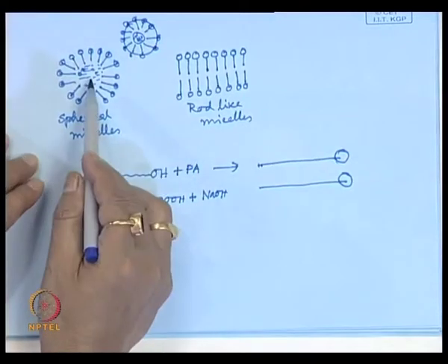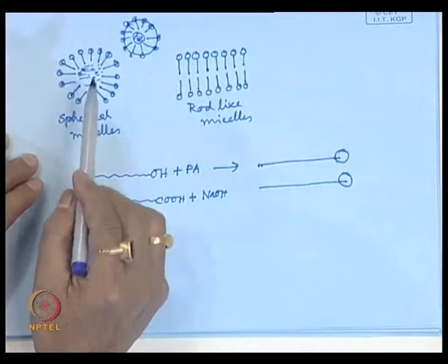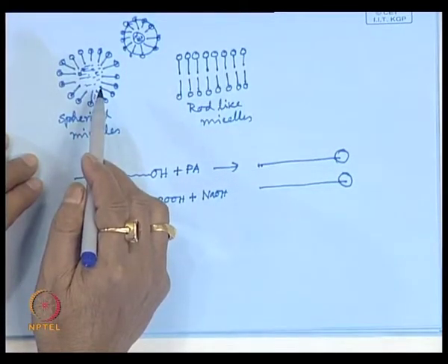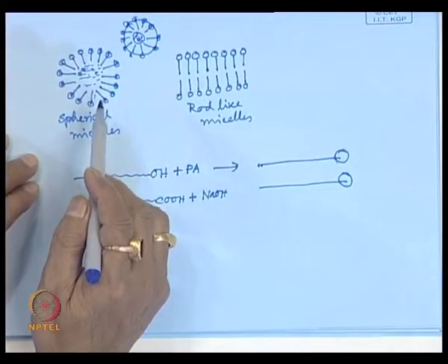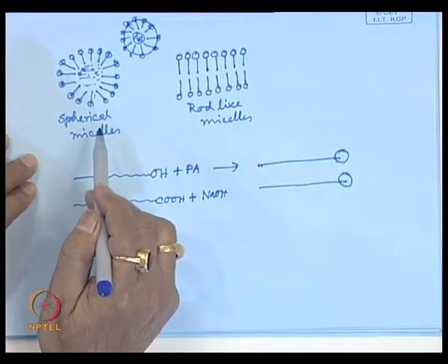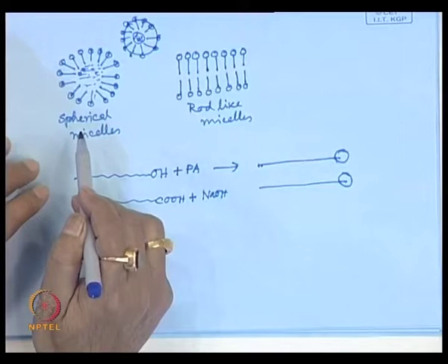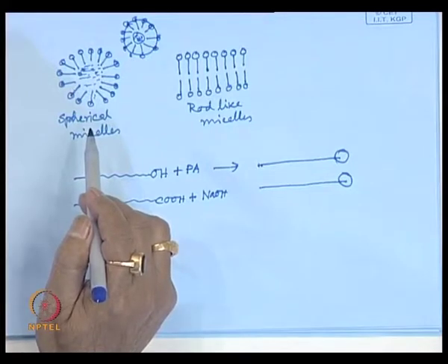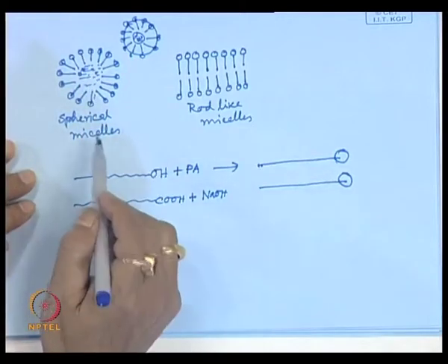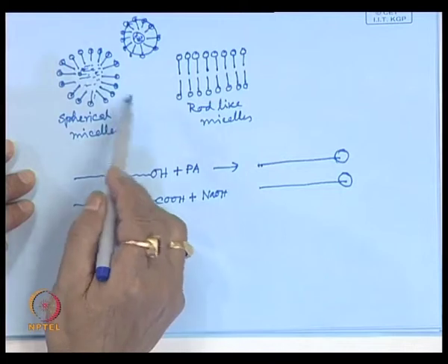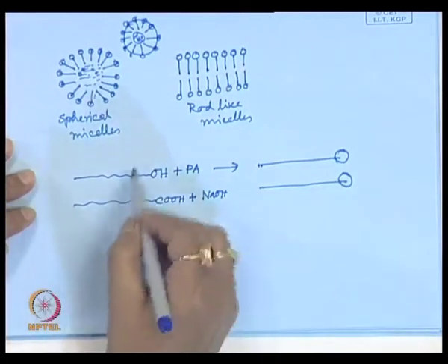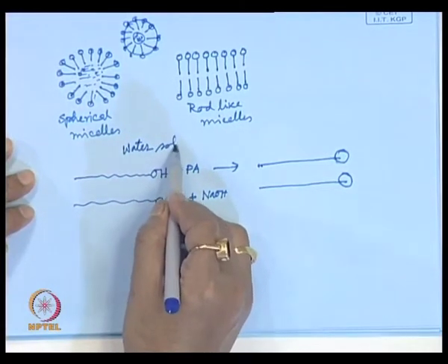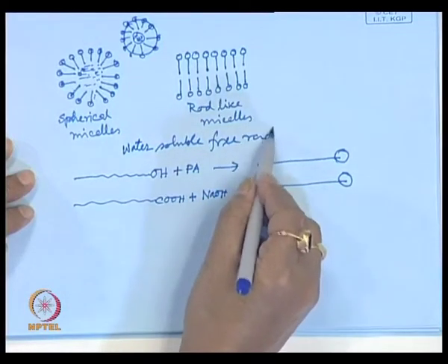Now, you want to polymerize this monomer trapped inside the micelle. For this we need an initiator molecule. In suspension polymerization, we deliberately added an initiator like benzoyl peroxide, azobisisobutyronitrile, or cumene hydroperoxide or dicumyl peroxide. Those get dissolved in the monomer phase, so the suspended monomer droplet is converted to a polymer particle. Here, what kind of initiator can we use? If we add benzoyl peroxide or AIBN, this emulsion polymerization cannot be done. For that we need a water soluble free radical initiator.